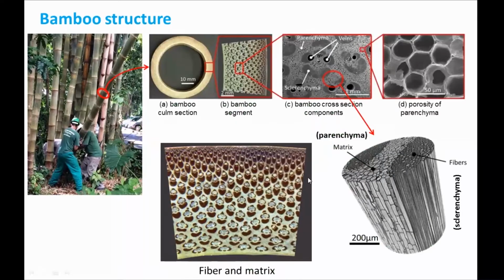Now the meso and microstructure of bamboo. After cutting, we cut a bamboo section here, and in this piece you can see a bamboo segment. The bamboo segment has three parts. One part is the matrix or parenchyma, which is the porous part. Another is the sclerenchyma or fibers, which are responsible for the resistance of the bamboo. And we provide tomography from a piece of bamboo here, and you can see the porous matrix and the sclerenchyma or fibers that are very dense, rigid and solid.